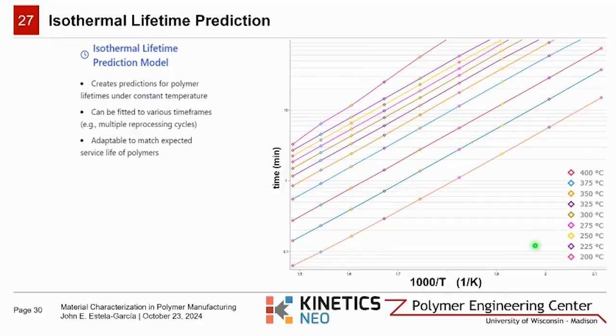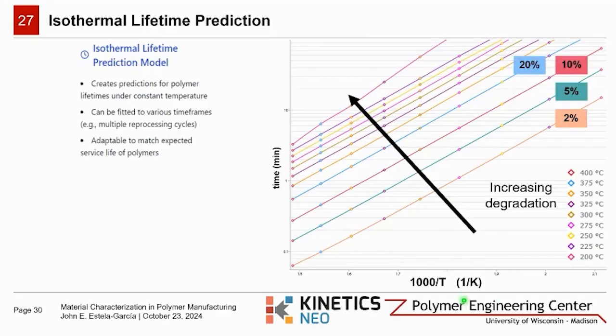The X-axis represents temperature, while the Y-axis represents time. And specific temperatures and exposure times construct the curves, with each curve representing a specific percentage of degradation. In this current curve that's constructed from the virgin polypropylene in the inert environment, we're observing lower temperatures requiring more time to reach the same degradation than at high temperature, which is reasonable since temperature is our main degradation impact factor here. This predictive capability is crucial for optimizing recycling processes and developing efficient pyrolysis schemes.